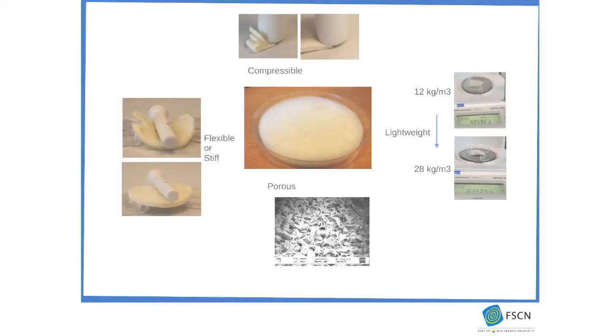So here is what we came up with. The material we produced is in the middle. As you can see, it's quite sponge-like, and it's compressible. It's also porous, from the same pictures, and by changing the process while making them, we can turn it into flexible materials or quite stiff materials. The density of all the materials we produced is between 12 kilograms per cubic meter and 28 kilograms per cubic meter. We think it's a pretty light material.